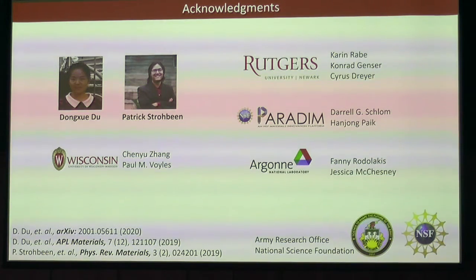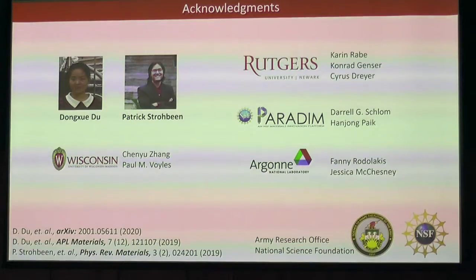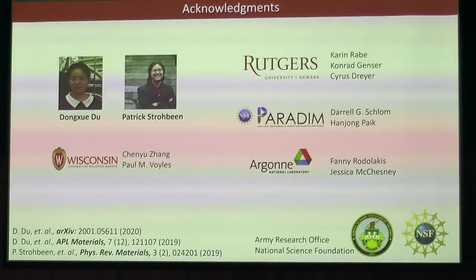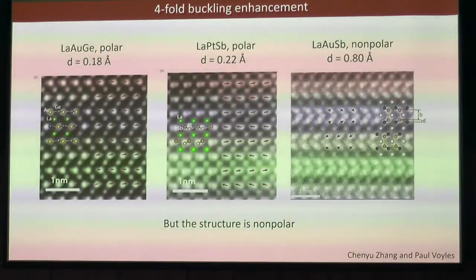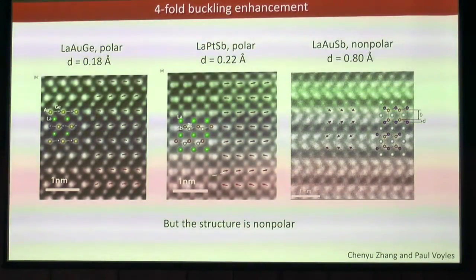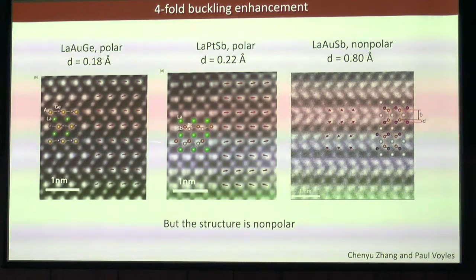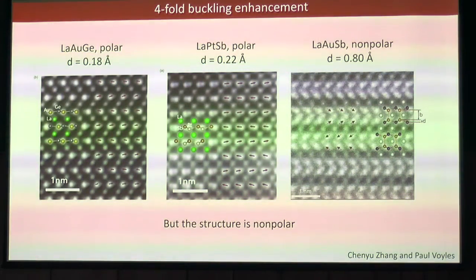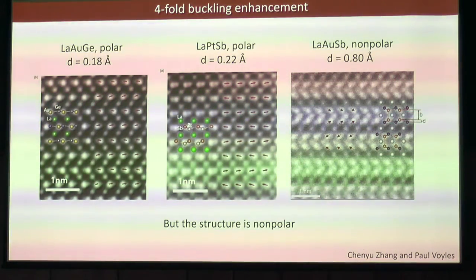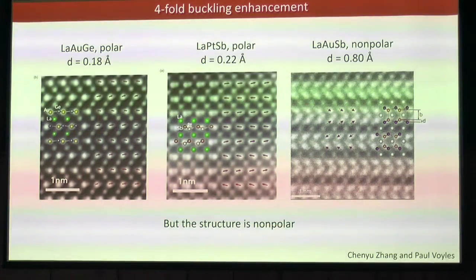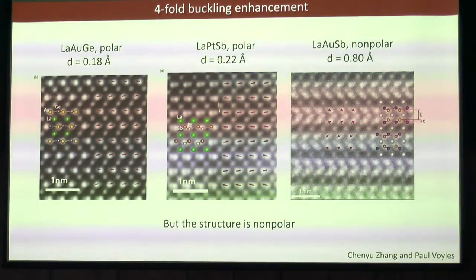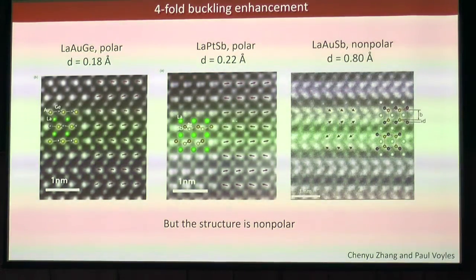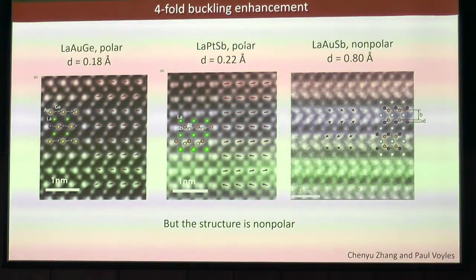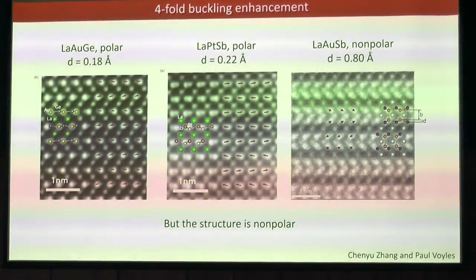So I was wondering, could you give a bit more detail of how your polar metal looks? I mean, you are still building a tri-layer with the polar metal in the middle, the one for which you measure this mysterious... So these are the two polar metals we talked about. The ones that we have the more detailed field maps are this compound. But so this is a thin film. What do you have at the bottom and at the top? So this layer is about 50 nanometers. At the bottom, we have sapphire substrate, C-plane. At the top, we've capped it with a very thick layer of germanium to prevent oxidation.